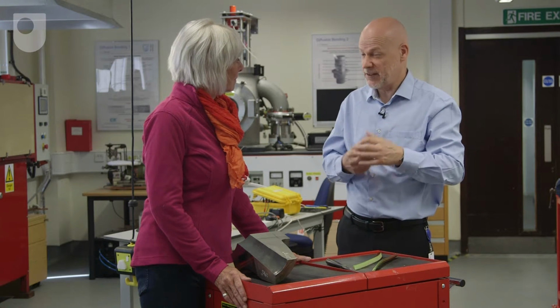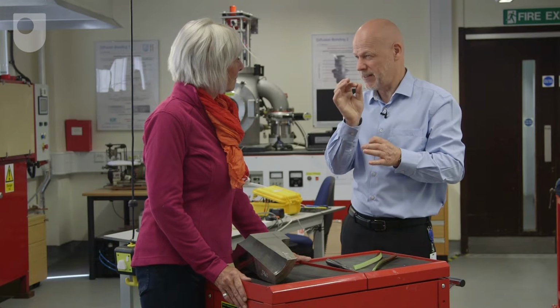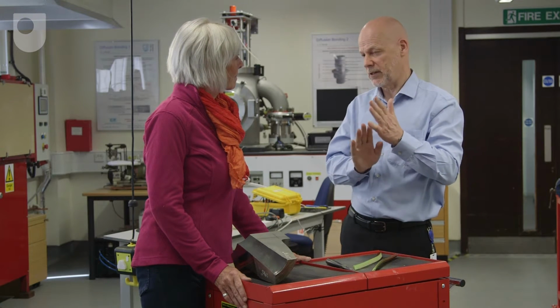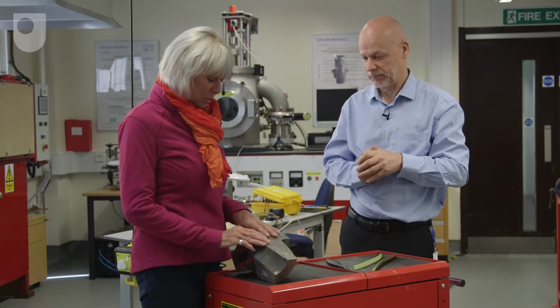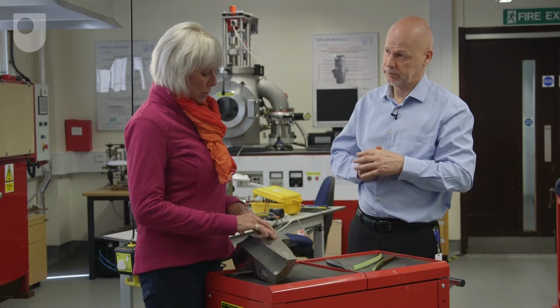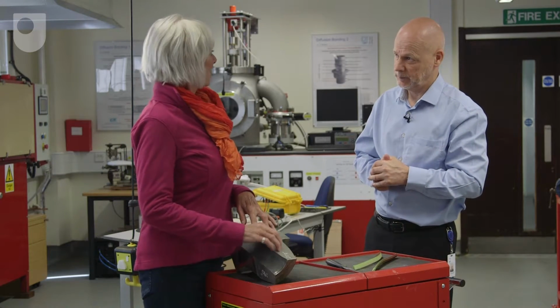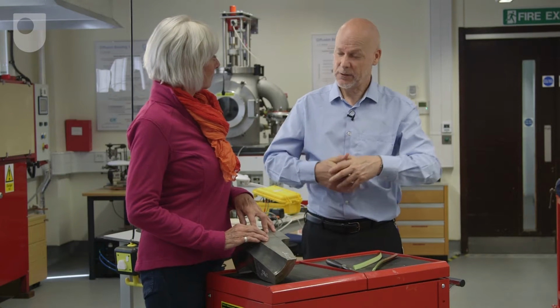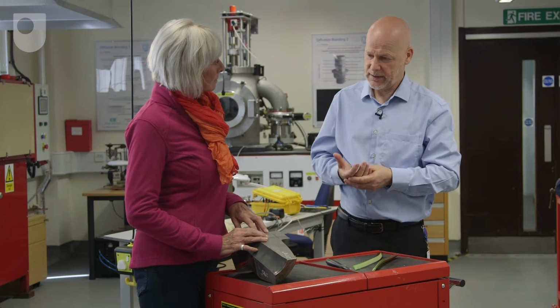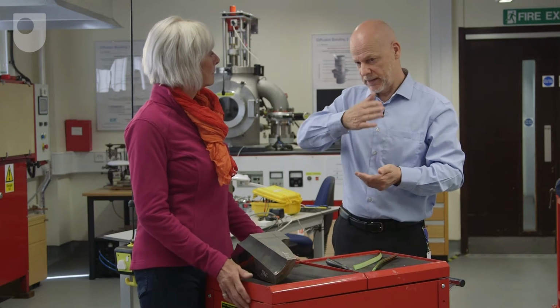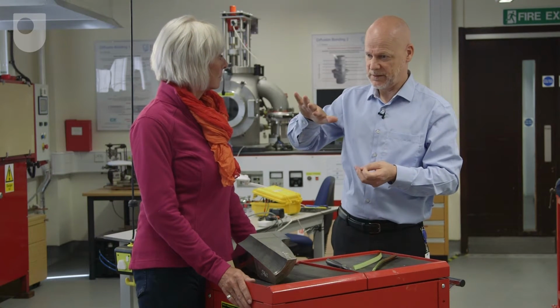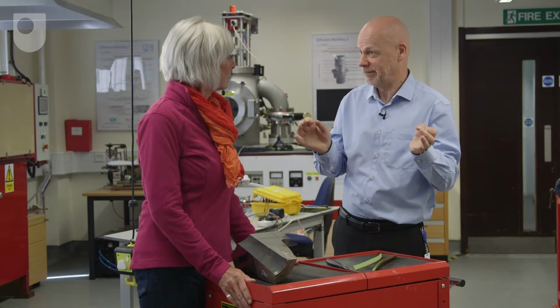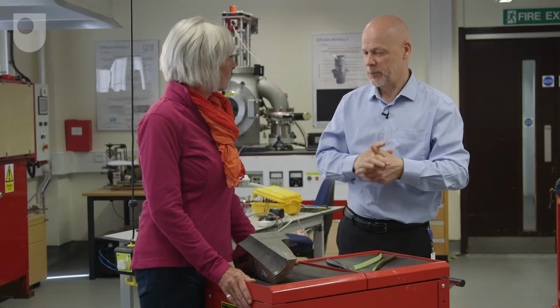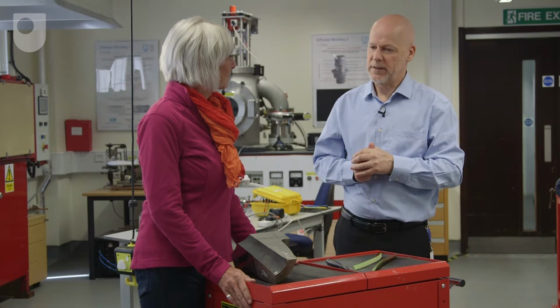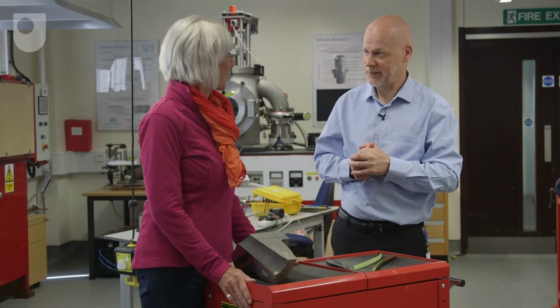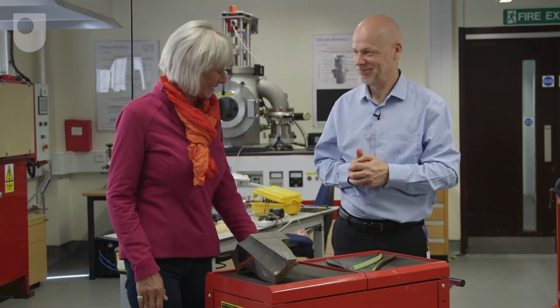Now this technique is actually very precise because these pits are very tiny, so you can get a very fine finish in a very controlled way. So once you've got the cut piece, how do you then measure and quantify the residual stress in it? Okay, so we then have two cut parts, and we take each cut part and measure the deformation, the shape or the contour of that cut surface. And we do that in a metrology lab with a coordinate measurement machine. Okay, you're going to show me that next? And I'll show you that next. Okay, yes, lead on.